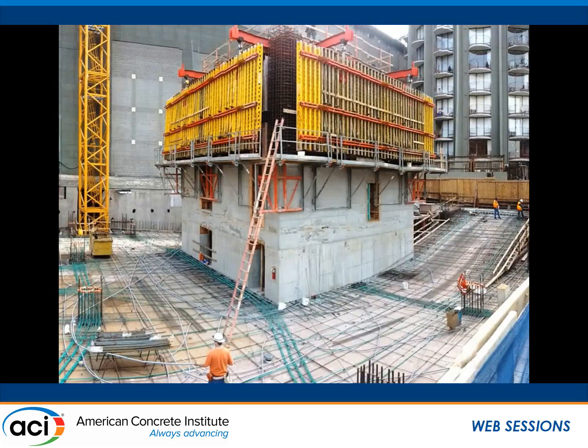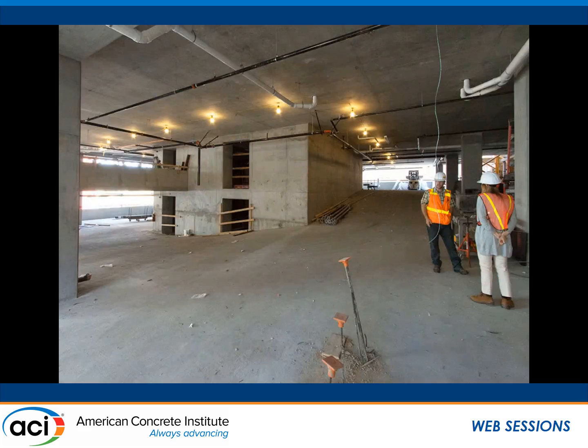And you could see a lot of coupling beams in this building. We spent a lot of time and took special attention to the design of these coupling beams. The way we designed those coupling beams is not only by the prescriptive code, but we also used the hysteresis loop from some of the diagonal coupling beam testing, and we implemented those in our performance-based analysis, which made the core much more efficient in steel quantities.